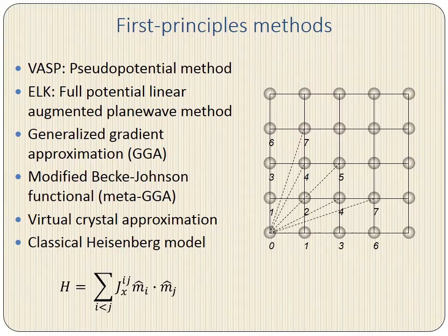To answer these and other questions, we turn to first principles methods. For the rest of my talk, I will discuss results obtained using 2 different methods: a pseudopotential method implemented in the code VASP, and also a full potential linear augmented plane wave method implemented in the code ELK. For all total energy calculations, we use the generalized gradient approximation, or GGA, to the exchange correlation potential. For investigating specific details of the band structure, we also used the so-called modified Becke-Johnson functional, a meta-GGA method that is used to replicate the band gap of a variety of semiconductors, with barium zinc arsenic being no exception.